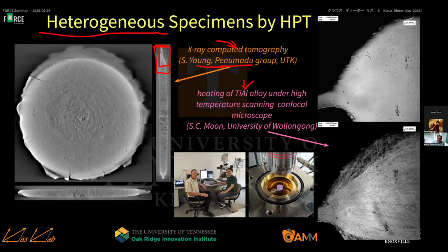And we put it on a heating microscope, a high temperature scanning confocal microscope, which the University of Wollongong owns in Australia. And upon heating, we see that there's different evolution of microstructure. This is different phase recovery and different stress state recovery and crystallographic recovery according to the locally different applied shear strain. So the samples are heterogeneous. That makes them interesting for many studies.